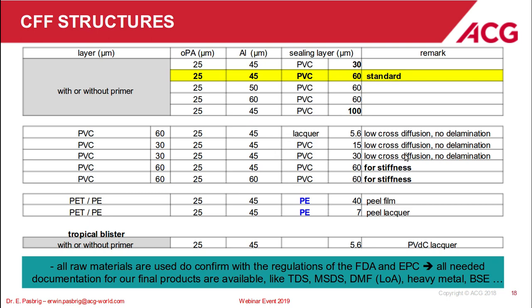The last two cold form laminates are based on polyethylene as a heat seal layer, PE in this case, and again on the outer side, the stiffening layer could be PE, so HDPE, or polyester, depending on requirements of customers. Mainly customers are using this when they say they do not want any halogen in the material, or they need a lower sealing temperature, then polyethylene is one of the choices. The last part, again with or without primer, is material for tropical blister, standard-wise 25 OPA, 45 aluminum, and 7 GSM heat seal lacquer.